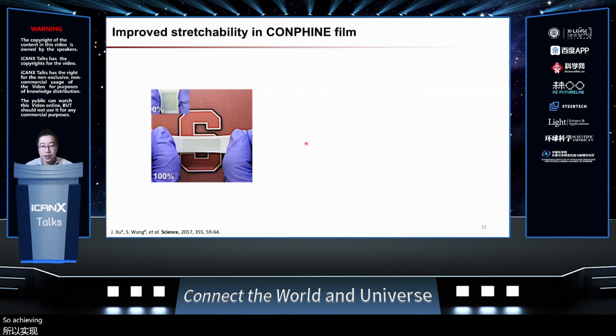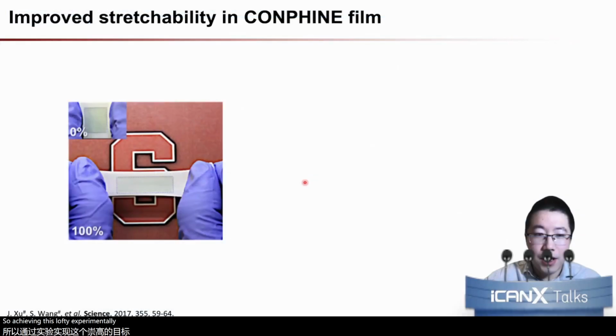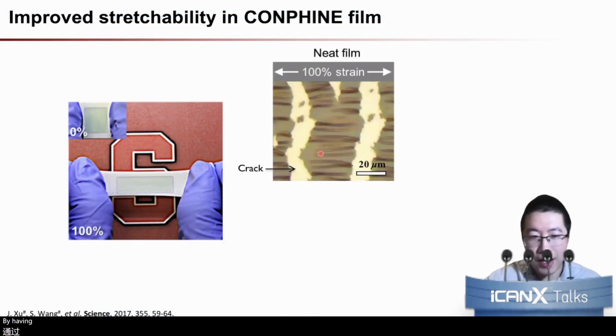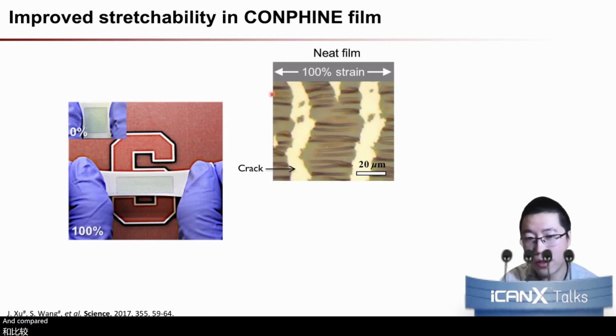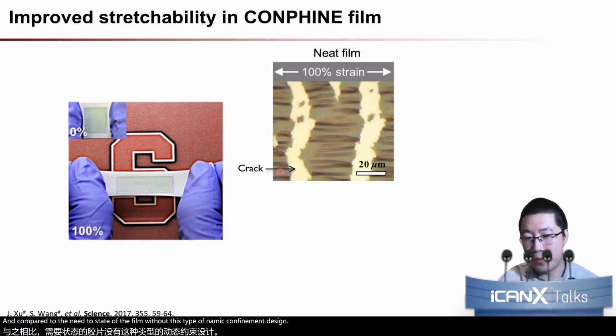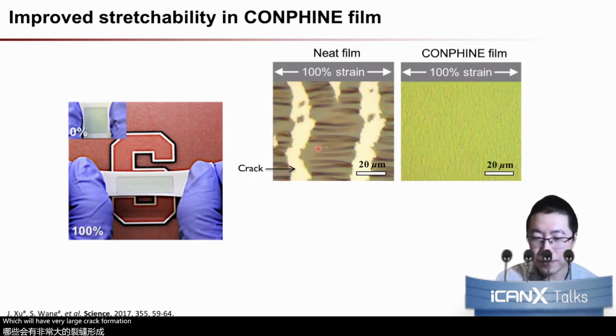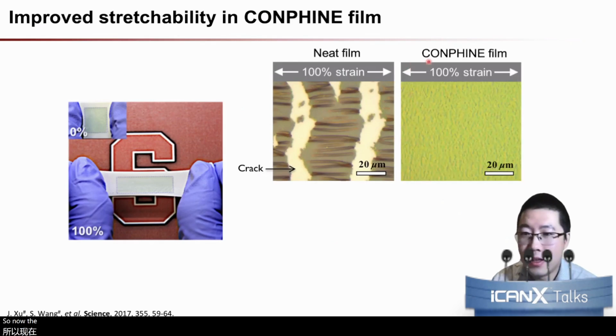Achieving this morphology experimentally, we have been able to verify that indeed the stretchability gets largely enhanced, having the capability of stretching to twice of its original length, compared to the neat state of the film without this type of nano confinement design, which will have very large crack formation. So now this so-called confined film can maintain the intact morphology up to 100% strain without any crack formation.